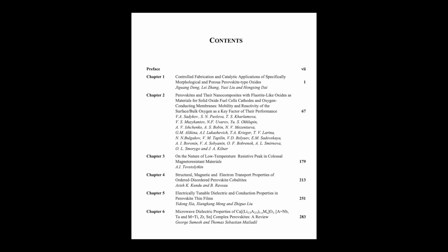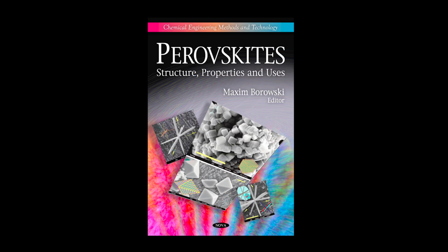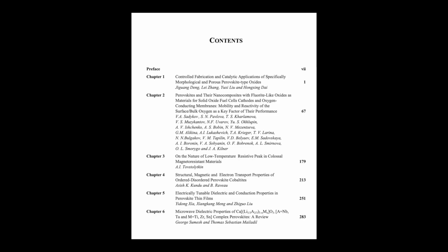In some early literature, several groups reported they'd successfully synthesized lanthanum manganite, La0.5Sr0.5MnO3 nanowires using hydrothermal methods, and they looked great under the electron microscope. But then, upon more rigorous subsequent analysis, using techniques like detailed X-ray diffraction, it turned out the nanowires weren't the target perovskite material at all. They were actually simpler wire-like nanocrystals of lanthanum hydroxide, La(OH)3, just a precursor phase that hadn't fully converted to the perovskite structure. Yeah, that slight slip in characterization definitely set back research for a bit.